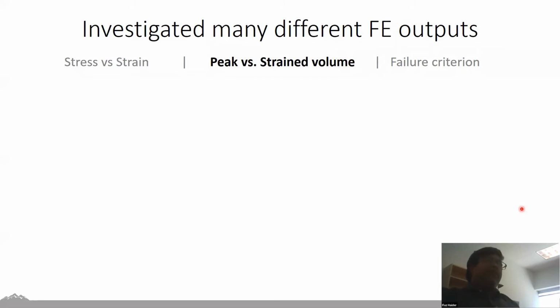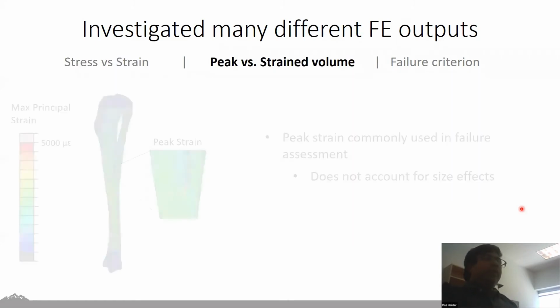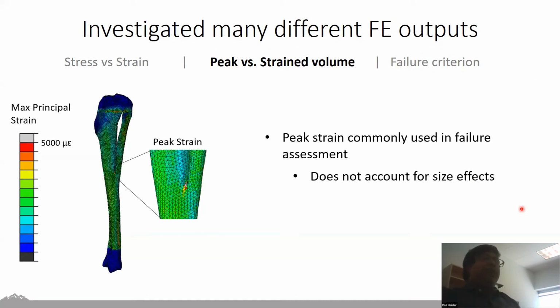The next thing we looked at was this idea of peak versus strained volume. And this is because in the literature, from what we saw, peak strain is really what's most commonly used in fracture assessment. But we suspected that this might not be a great measure because it doesn't necessarily account for size effects. And I think a great example is this one really extreme example from one of our tibia. As you can see, the peak strain is really just happening over a few elements in the tib-fib junction. And yet, when we look at the rest of the body, there are sites of high strain all throughout. We suspected that a measurement of peak strain doesn't necessarily account for what's happening elsewhere. And what's happening elsewhere probably has some effect on the fatigue life, given what we know about size effects.